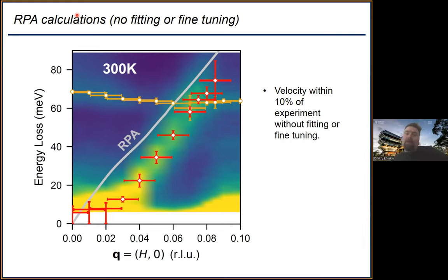If you extend this plot to higher momenta and energies, where the other phonon modes are, do they hybridize with each other, with this demon? Well, the demon actually damps out above this and you don't see it at all. Oh, I see. So 0.08 is the critical momentum of the demon. Beyond that, it's completely damped, which is actually quite like a plasmon. If you look at the width of this thing, it goes like Q squared, which is sort of what you expect for Landau damping in a Fermi liquid. Oh, I see. So it doesn't live to a large Q.